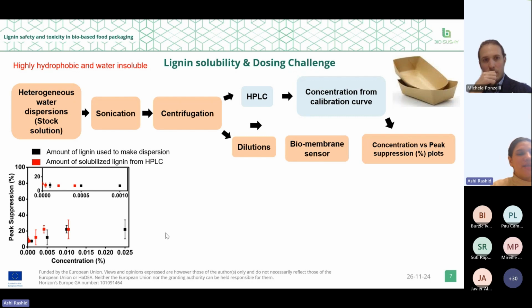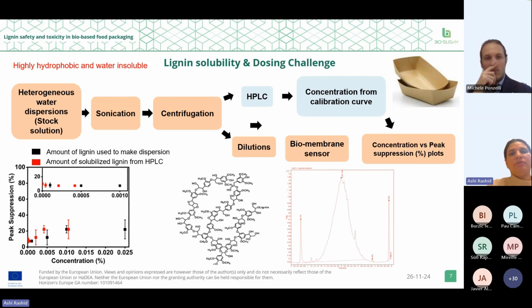So here we can see that the amount of solubilized lignin is relatively much lower than the amount of lignin used to make these dispersions. From here we can see that, due to the very complicated structure of lignin, it's a complex biopolymer, and in solubilized form it can exist in different oligomers in the form of lignin phenols.